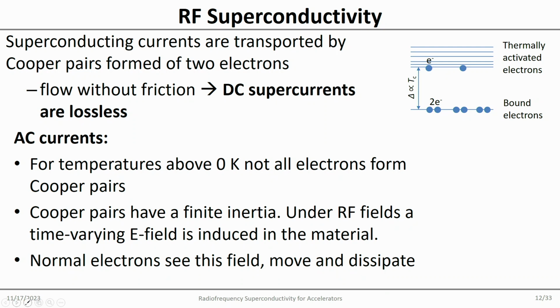But what we have here is radiofrequency superconductivity, and that has some particular things. As I said, DC supercurrents are lossless, but what about AC currents? For AC currents, we have these Cooper pairs, but not all electrons will form Cooper pairs. If you have a temperature above 0 Kelvin, you always have some electrons being excited into a state. So not all electrons will form Cooper pairs. Now the Cooper pairs have no resistance, but they have inertia.